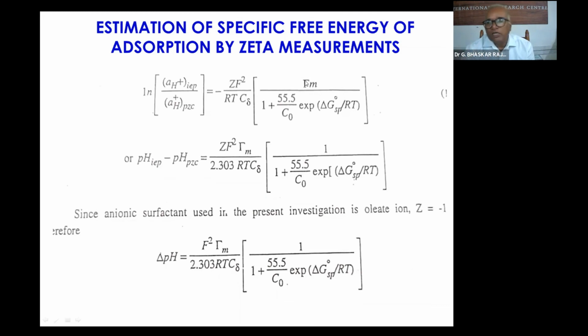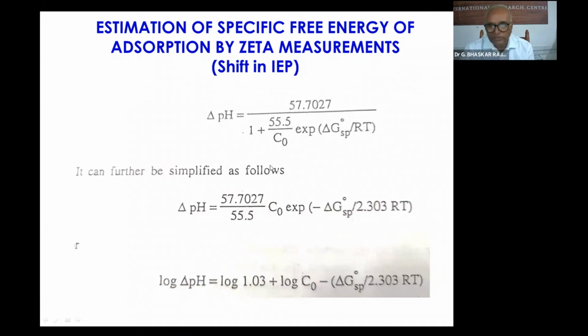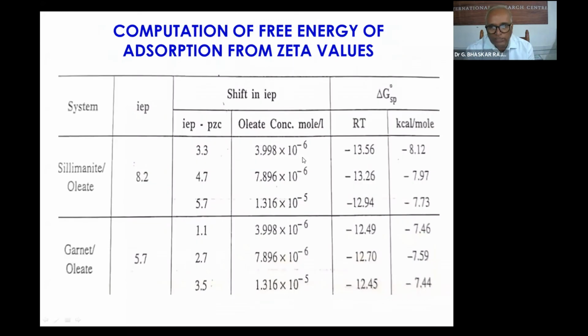By measuring the adsorption, we can measure how much oleic acid has adsorbed on the surface of sillimanite. We can measure it by other methods. That amount of oleic acid adsorbed is so many moles per centimeter square. This is the adsorption density. This is the initial concentration of the oleic acid, the C0, so that we can ultimately measure the shift in IEP.